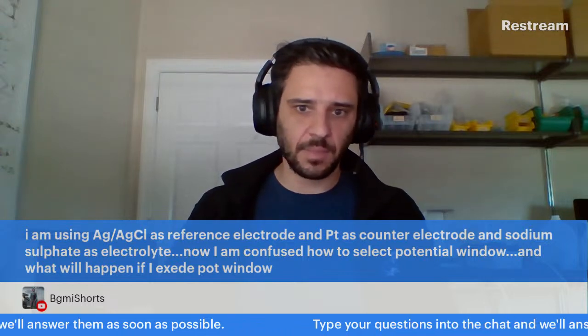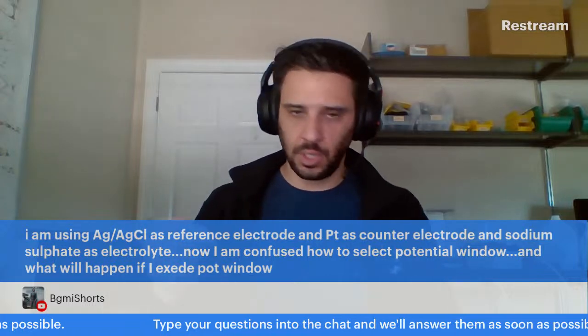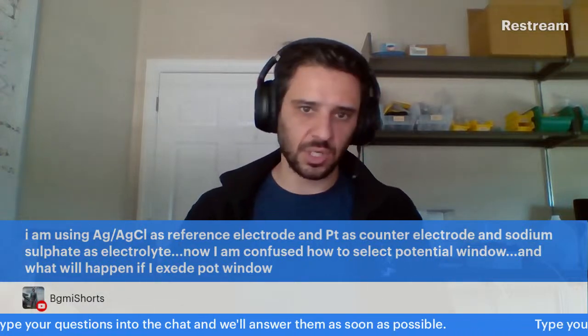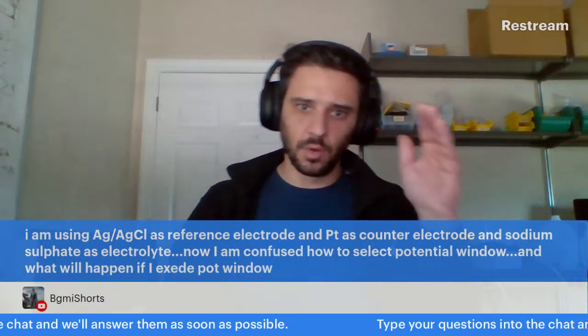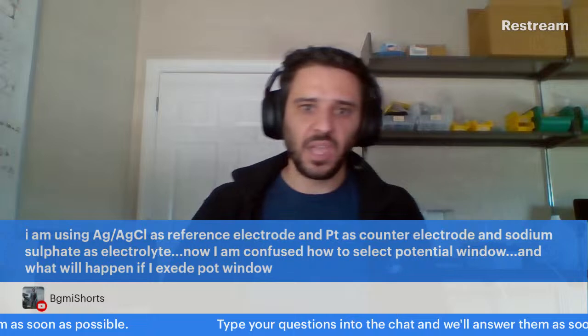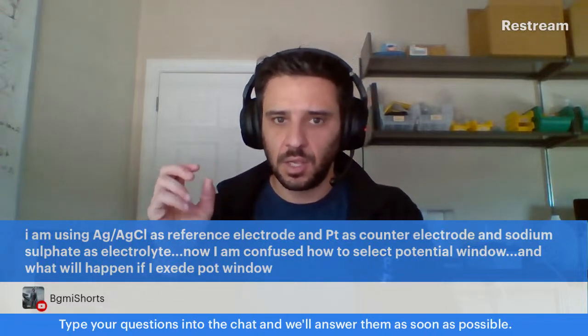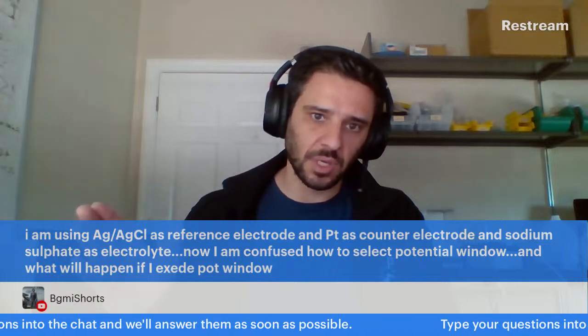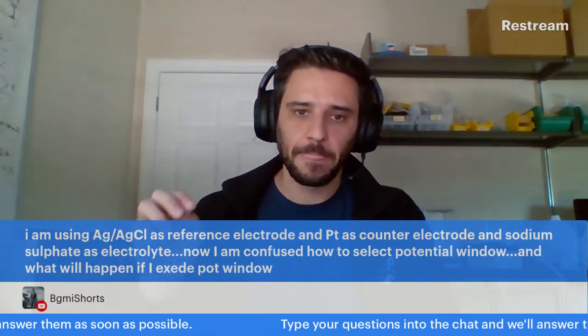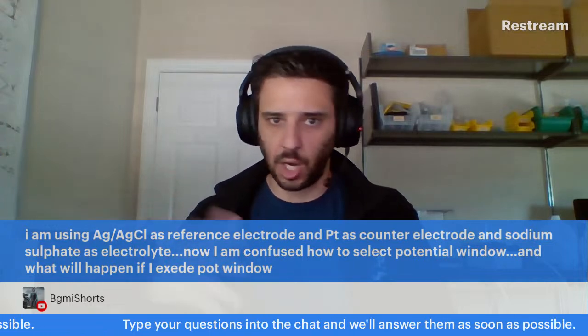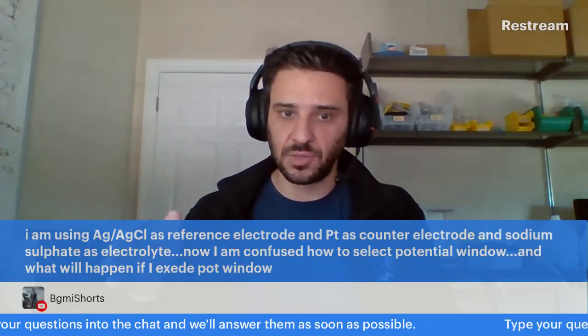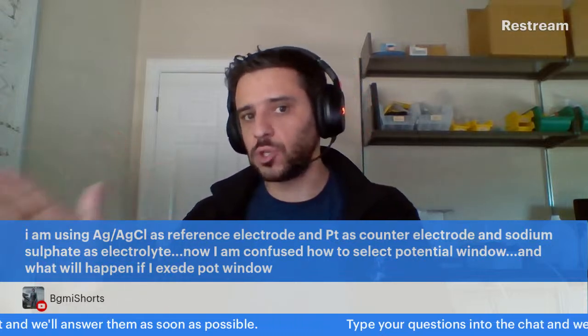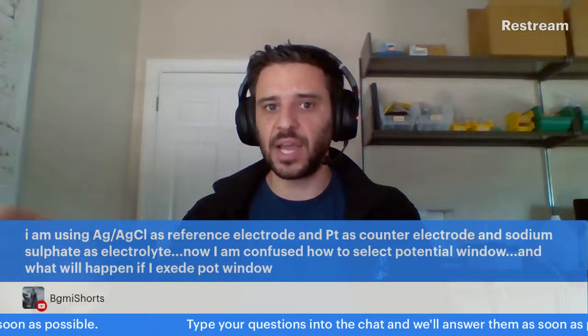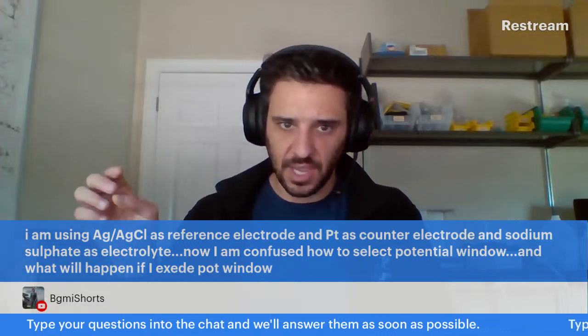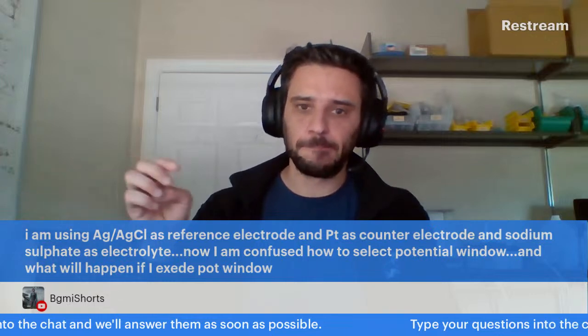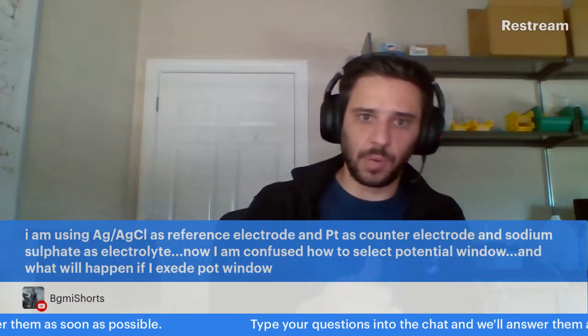If you only exceed the potential window by a little bit, you're just going to do more of the oxygen evolution reaction at the positive end, or the hydrogen evolution reaction at the negative end. If you really, really greatly exceed the potential window, you could run into some problems. For example, if you have a glassy carbon working electrode, and you go way too positive a potential, you will oxidize the carbon electrode itself, and you could damage it permanently. So you want to be careful, and you could have similar problems if you go too far negative.